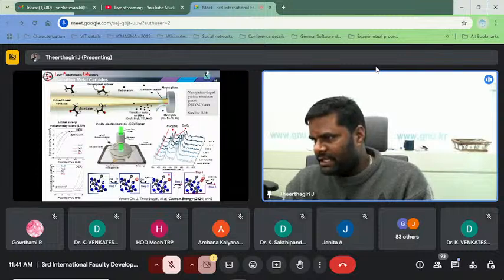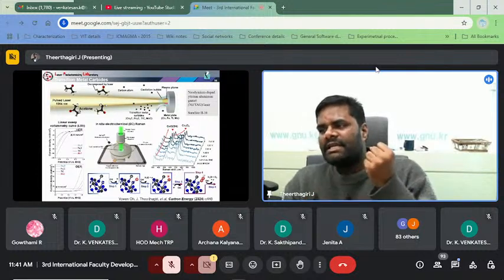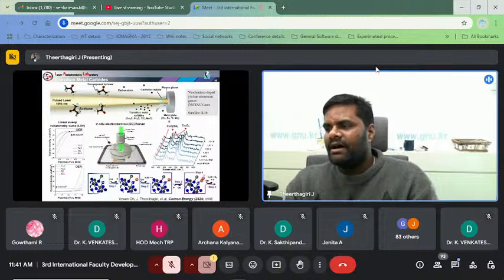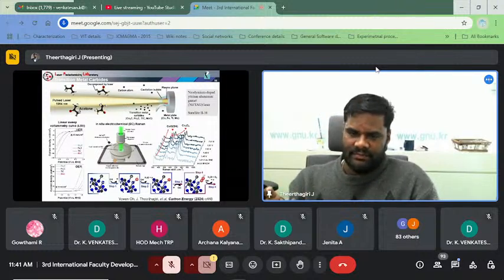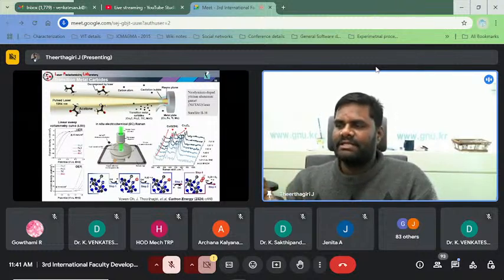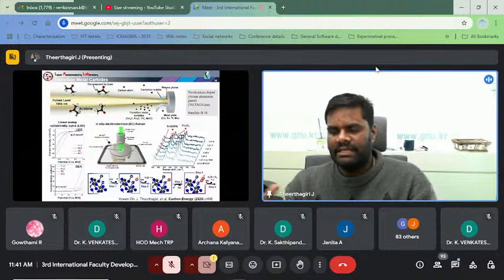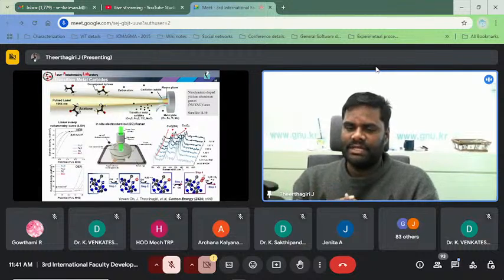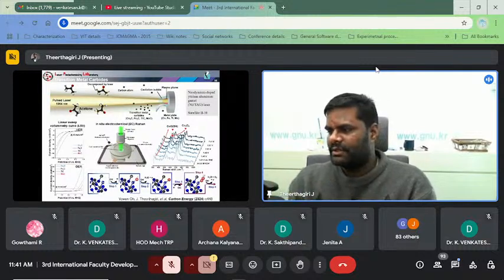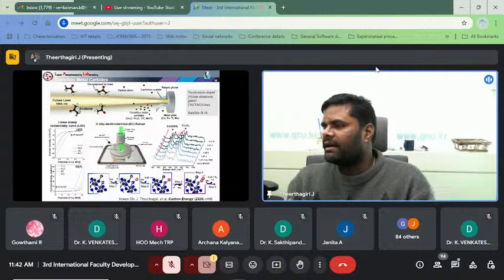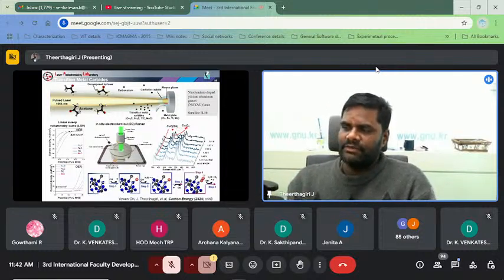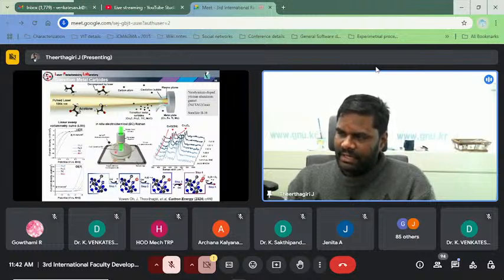So what happens in alkaline medium? It easily attacks oxygen and forms oxyhydroxide as active sites. These are the reactive species or active sites. We can further validate this using DFT theoretical studies also. When there is a prolonged oxidation reaction, it is again converted into cobalt oxide. This is the observation from our studies.